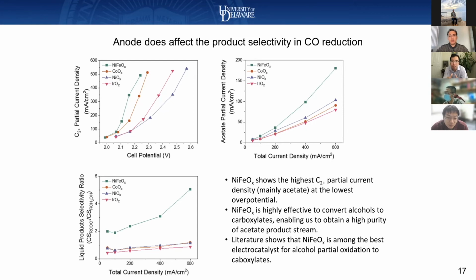And what we did here is to keep the anode loading exactly the same. So roughly speaking, the active site is way more than sufficient to drive OER. We just want to see the side effect on this ethanol partial oxidation. I see. Basically, the anode side has very sufficient OER process, right? Yes, OER is still dominant on the anode. I see. Thank you.